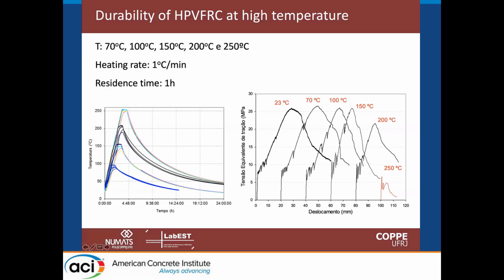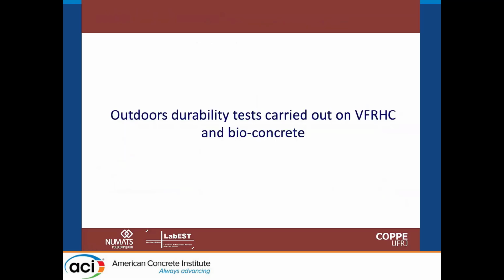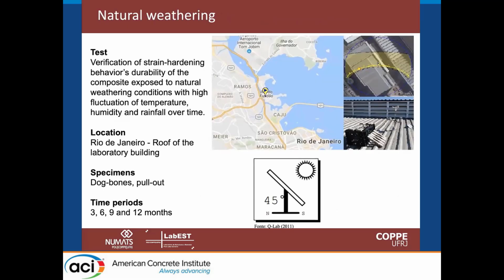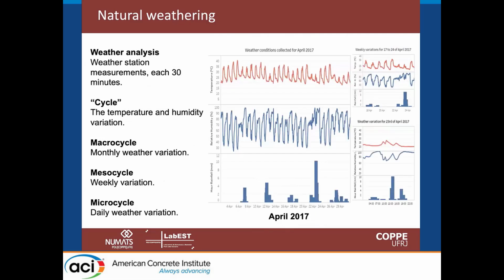I would like to say that without doubt, up to 150 C, we keep basically the same properties as at room temperature, and even up to 200, we still keep 75 to 80% of the properties of the normal material. One important thing is to see in tropical countries how the natural weather, by thermal hydro cycles, can affect the behavior of the material. In these tropical areas, we have very quick cycles of wetting and drying, because we have rain and immediately after a few minutes, we have the sun coming out again.